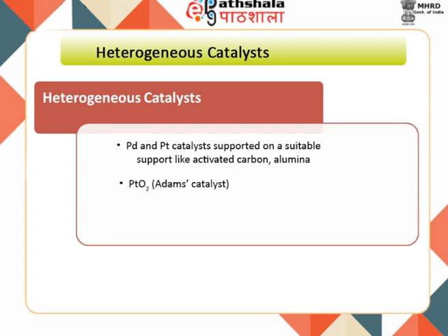Platinum, which is pyrophoric and difficult to handle and optimize for a reaction, is not employed itself as a catalyst, but is often used in the form of its oxide, which is reduced to metallic platinum by hydrogen in the reaction medium. Nickel-based non-precious metal catalysts have also been developed as economical alternatives, but they are often slower in reaction or require higher temperatures or pressures.